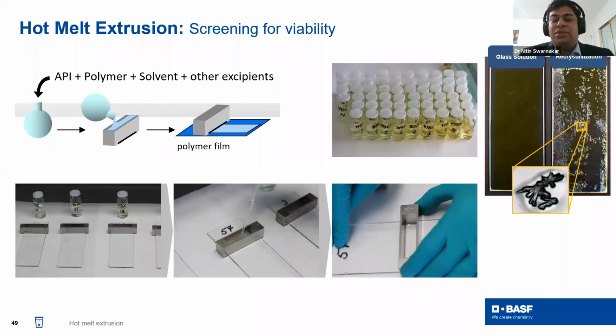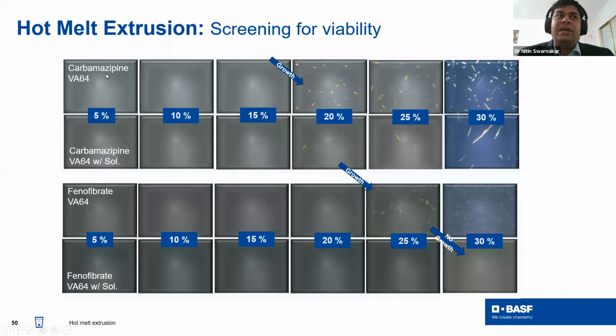You can store it at room temperature for 30 minutes, and then in vacuum you store it for 30 minutes again at 10 millibar and 50 degrees centigrade. And you can compare whether it's making a glass solution or it is crystallizing out. So you can do this kind of experiment to understand what ratio you need. You can see the example, carbamazepine with VA64: you can see crystallinity once you increase the amount of drug. At 20%, you can see the crystal. In solution form, like with a solubilizer also, you can see the crystal.